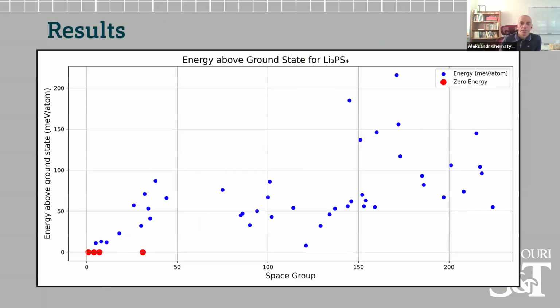So we run these calculations. These are the results, and these are the results for the lowest energy structures found in every space group that was considered. In this case, you can see that there is still a good number of blue dots. So we still have a reasonable number of space groups in which the simulations were performed. And you can see that the red dots are indicating the lowest energy that we have found.